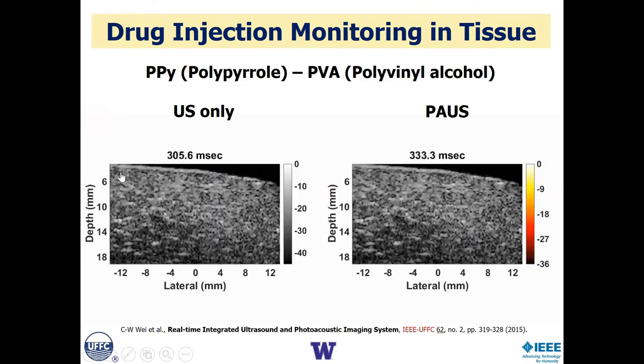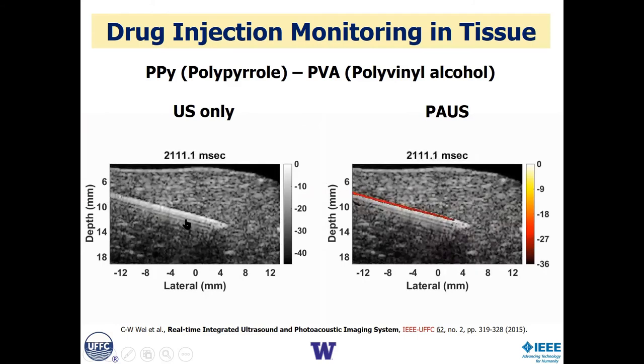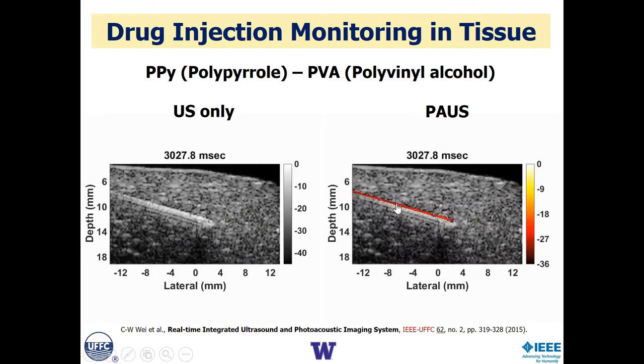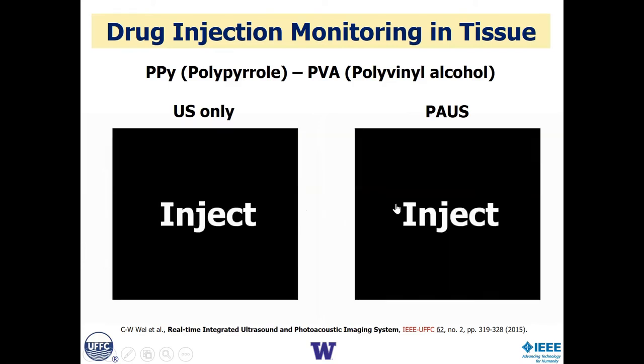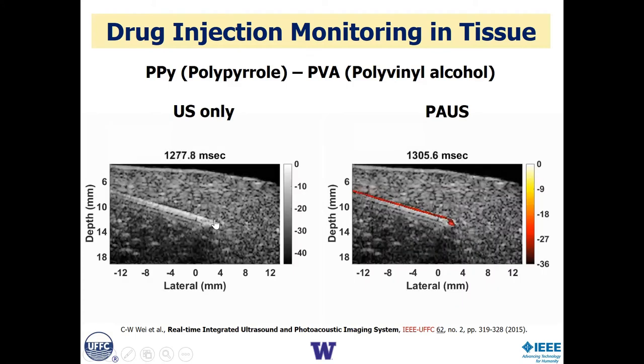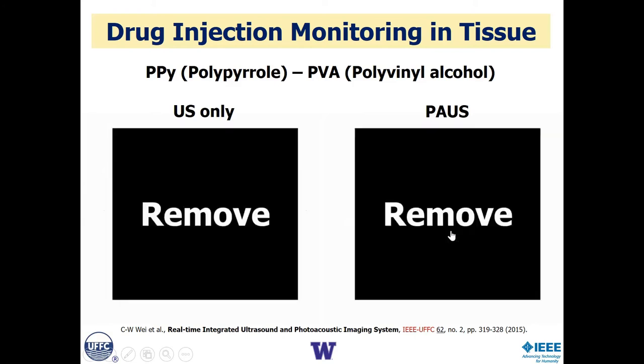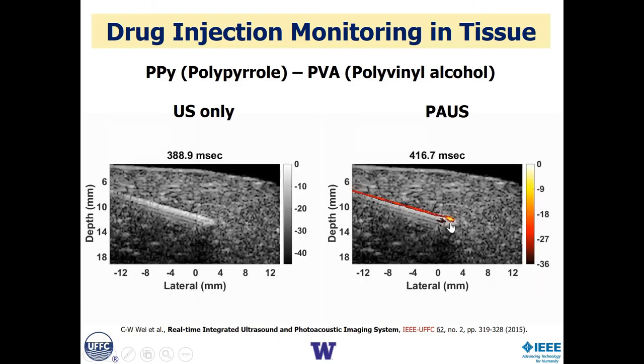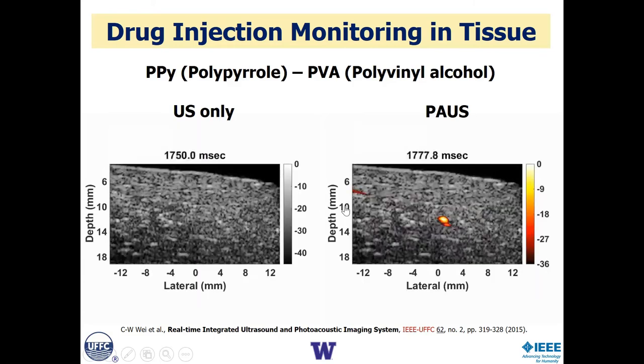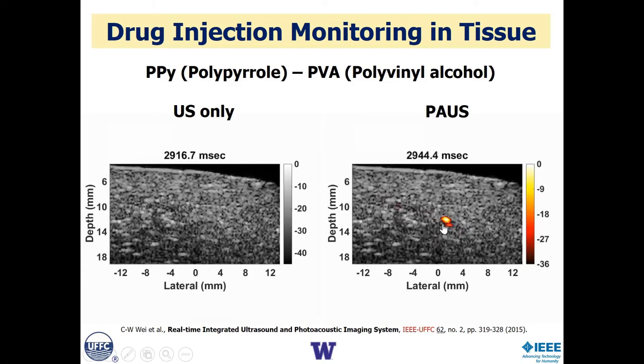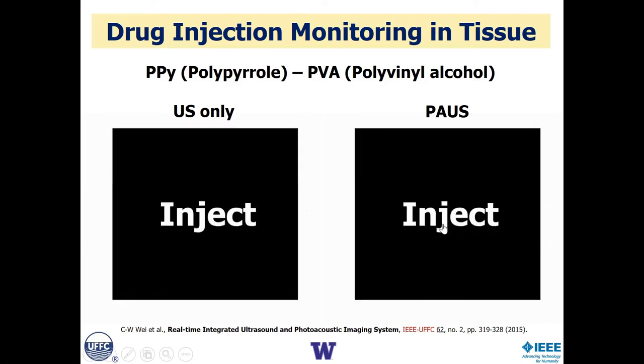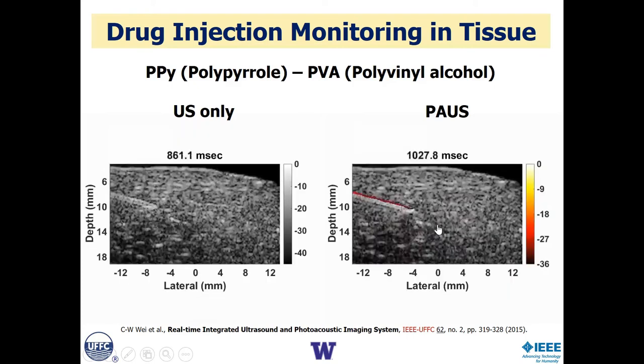Okay, just as you do to deliver the drug, you bring in a needle, you can see it on ultrasound. You can also see it on photoacoustics because of course you can see the optical absorption in the metal. You'll now inject the contrast agent. It's a fluid, so you can't see it in ultrasound, but you can molecularly label it optically. And so we can now see the drug. So we don't see anything here, but we see the drug. We can see how the drug's distributed, how it's taken up by different tissues, and do this not just over minutes, but over hours to days later, since this is a pure molecular label.